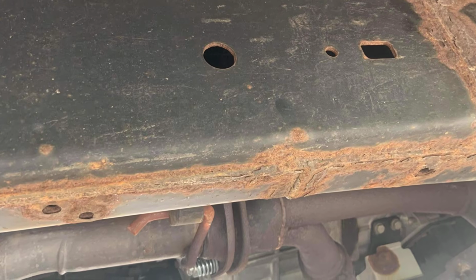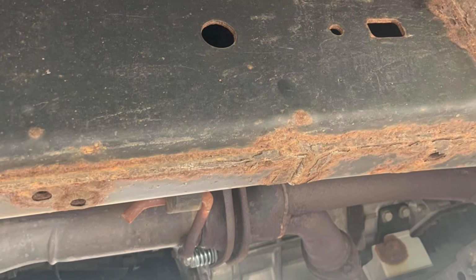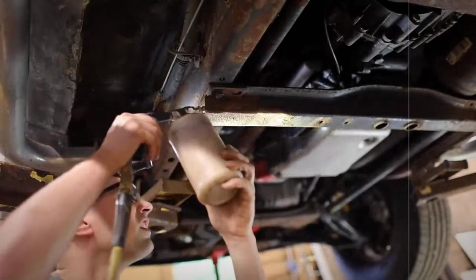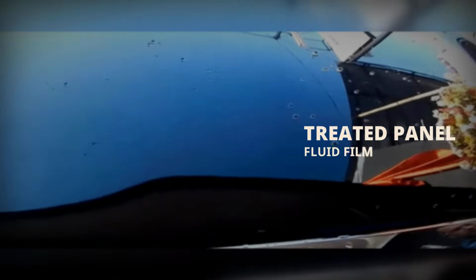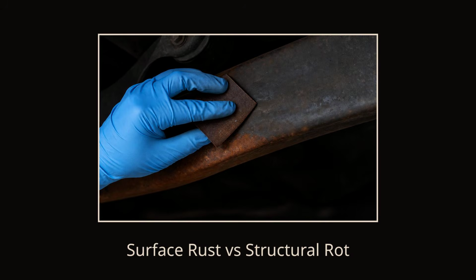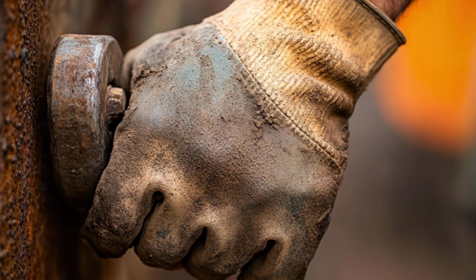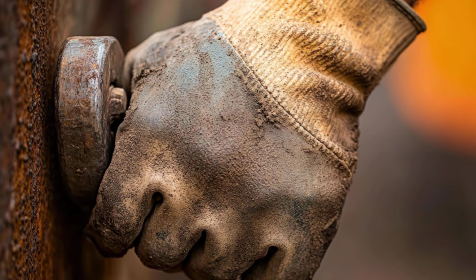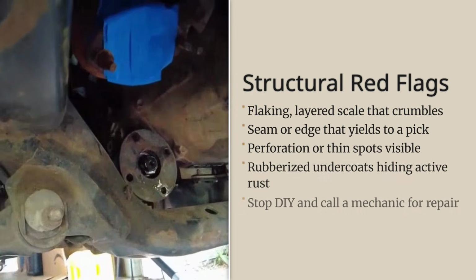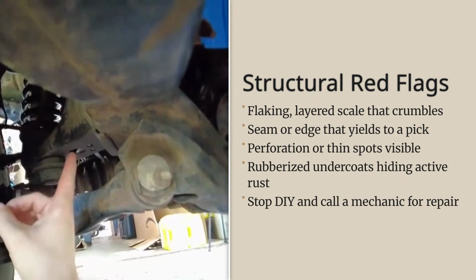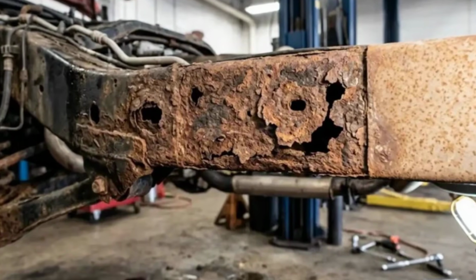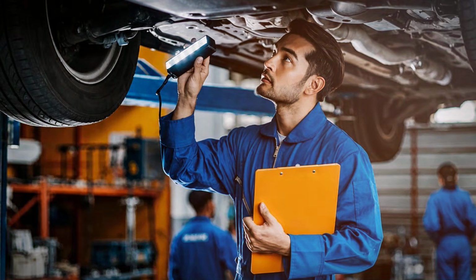The reason lanolin film works is precisely because it doesn't seal. It stays fluid, creeps into every seam and scratch and weld gap, and keeps oxygen and moisture off the metal without creating a pocket where corrosion runs in the dark. If you spray fluid film over existing light surface rust, the reddish-brown dusting on an older frame, that's fine. The oil penetrates, displaces moisture, and slows the reaction. If you find heavy scale, flaking sections, or a seam that gives under a pick, stop. Inspect first. Know what you're coating before you coat it.